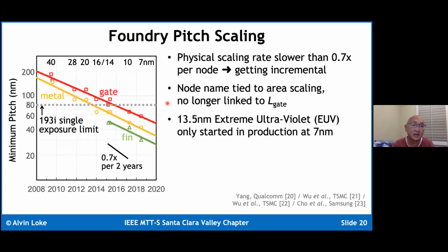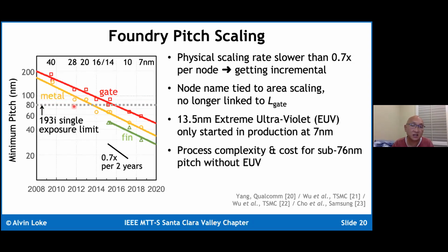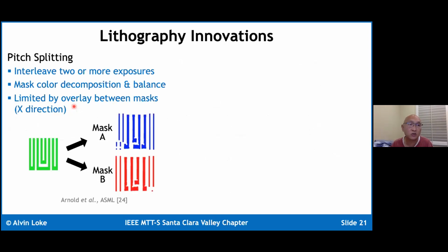Okay, but before EUV was introduced, basically we were stuck with using 193 nanometer wet immersion lithography, which has a single exposure pitch limit of about 80 nanometers. And so when we needed to go below the single exposure limit, the industry adopted a host of different process complexity and cost to get these features. Okay, how will we do that? So some of these lithography innovations are shown here. One is pitch splitting. The idea with pitch splitting is you would interleave 2 or more exposures to print a given layer.